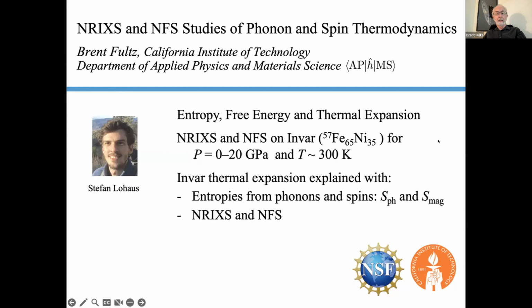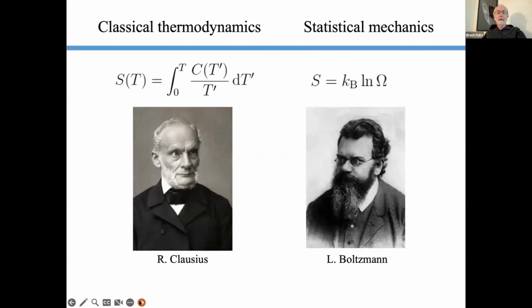And he has got a study on iron 65, nickel 35 Invar, which, as you know, has zero or near zero thermal expansion around room temperature. He did experiments as a function of pressure around room temperature, and we can explain the Invar effect thermodynamically now. The new piece of it is not the magnetism, but it's the phonon part, which has been neglected up to date. So I'm going to start by talking about thermodynamics.